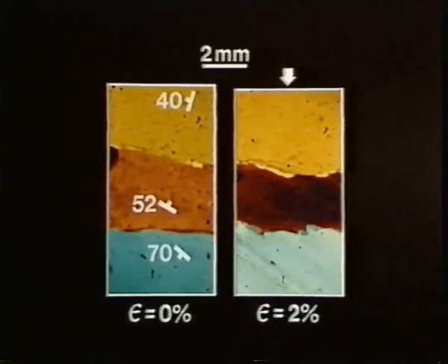The original starting material has basal planes with orientations as indicated by the dip and strike symbols. The basal planes in both the blue and the adjacent orange grain are favorably oriented for easy glide once deformation begins. The yellow grain is in an orientation for hard glide.